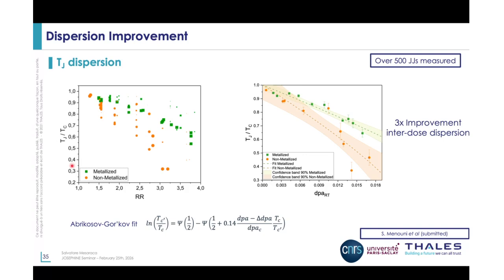And already on the graph on the left, where we have TJ over TC, so it's normalized TJ over TC, you can see that the non-metallized ones have a very high scattering, very high deviation. There is no clear trend that can be evaluated from this graph. Well, for the metallized one, you can see that there is some kind of linear trend, and the scattering is way less pronounced.